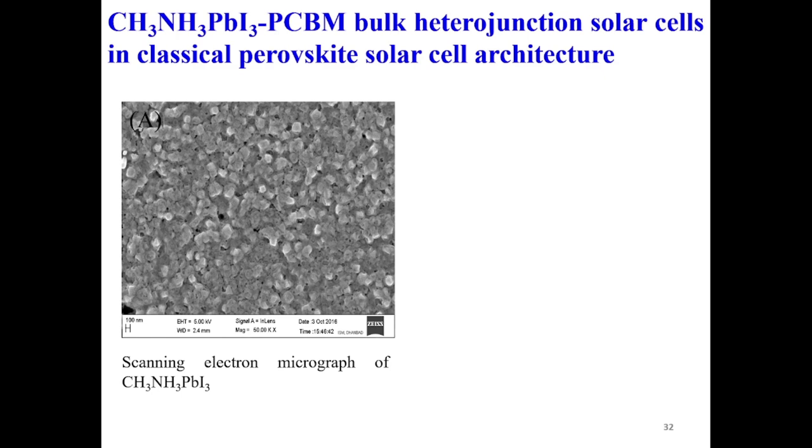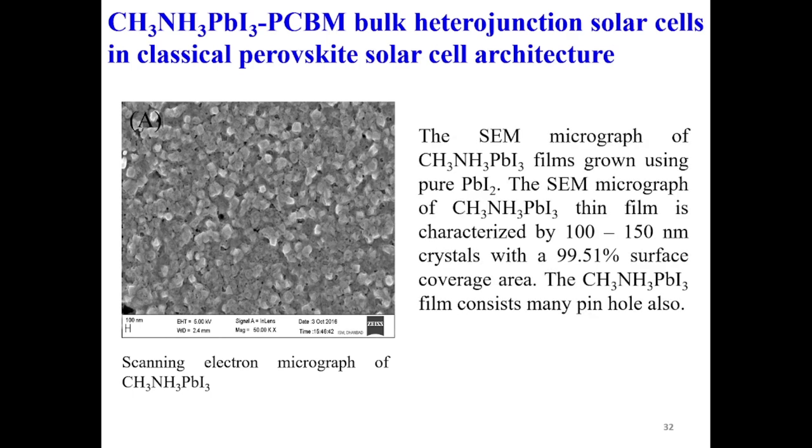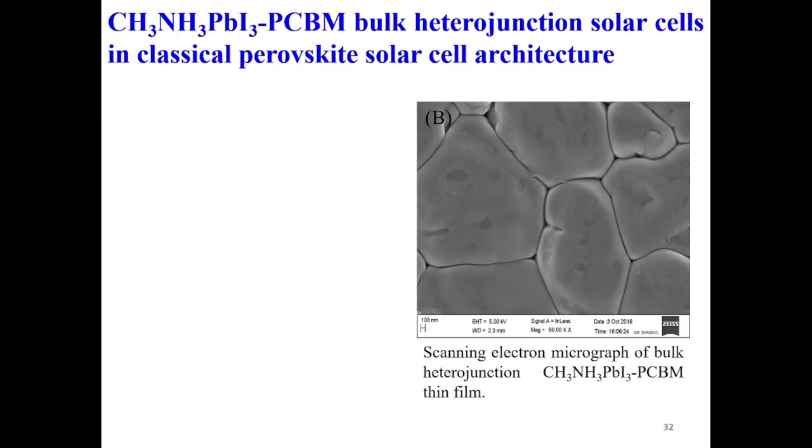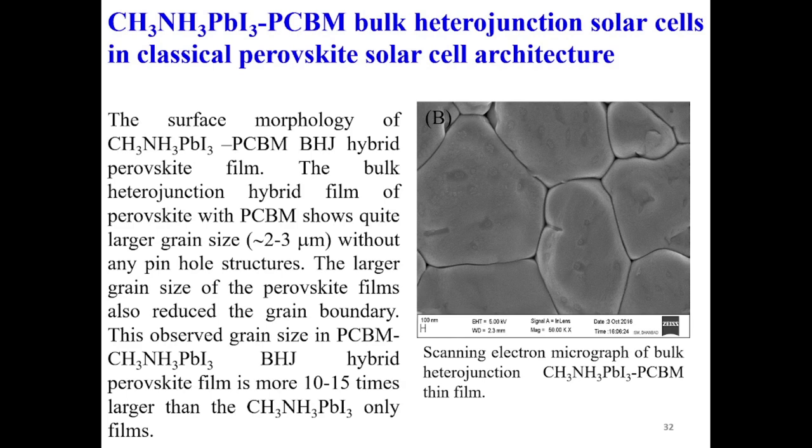The scanning electron microscope shows crystallinity, and the coverage is good here. If you see, interesting and so big grains we have achieved, and these grains have less voids. The good coverage of surface - the morphology of these films is good.